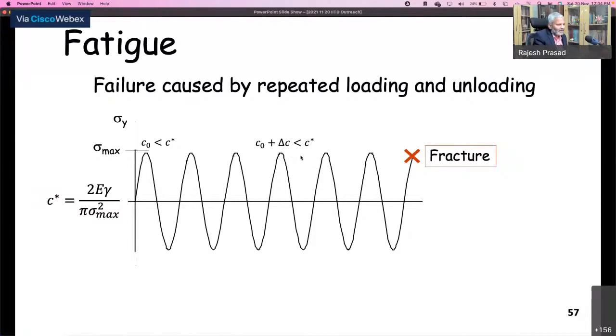But then finally, during the growth process, if the final crack size reaches C star, because it is growing and C star is constant, then CF is equal to C star, and fracture will happen. This is called subcritical crack growth.